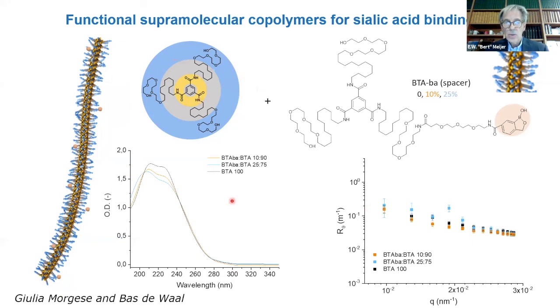And everything that we do optically or with scattering techniques will show that this type of molecule really intercalates into the fiber and forms a random copolymer as long as you don't go beyond 25%. And typically we're going to 10% of that functionality, which is then randomly oriented. But what does it actually mean, randomly oriented?